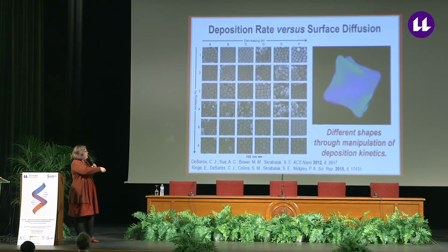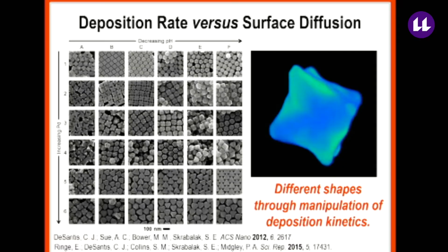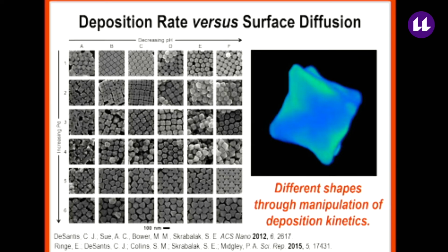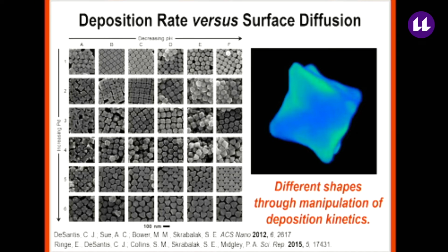So these different shapes are being accessed because these changes in reaction conditions are simply modulating the rate at which the metal is depositing on the seeds relative to the diffusion of the adatoms on the surface. So when the rate of metal deposition is fast relative to surface diffusion, the atoms that are adding can get stuck in kinetic or higher energy locations. So we think of the branched nanostructures as kinetic structures, whereas the more polyhedral forms are thought of as more thermodynamically favored structures, because now the rate of adatom addition is slower relative to surface diffusion, so they're able to find the more thermodynamically favored positions.